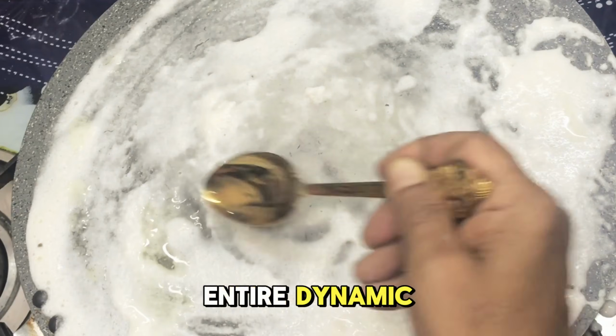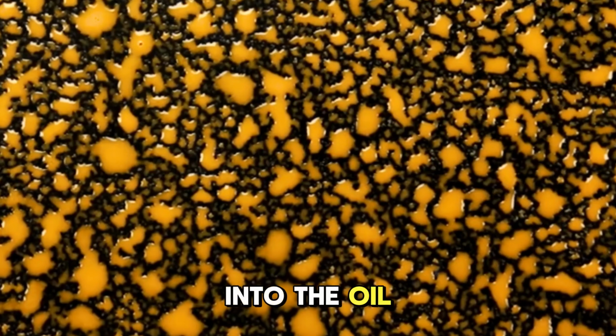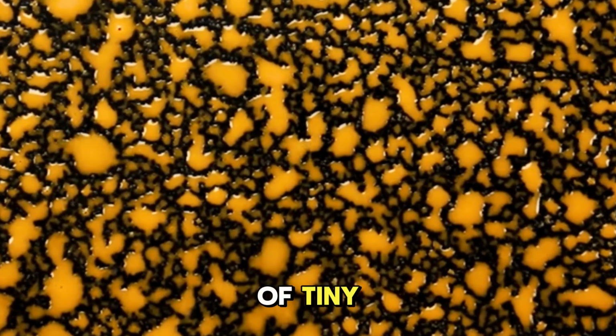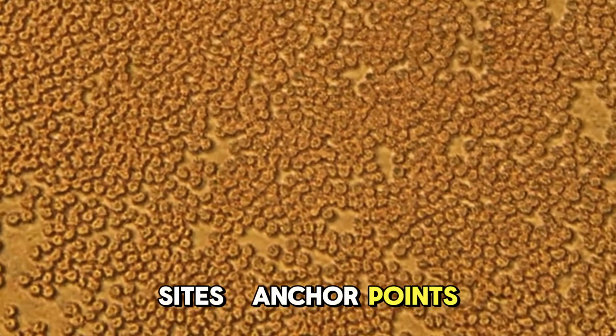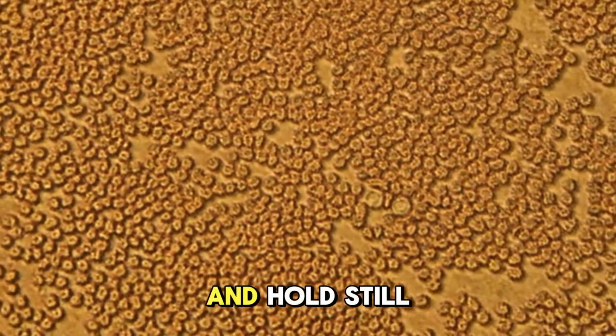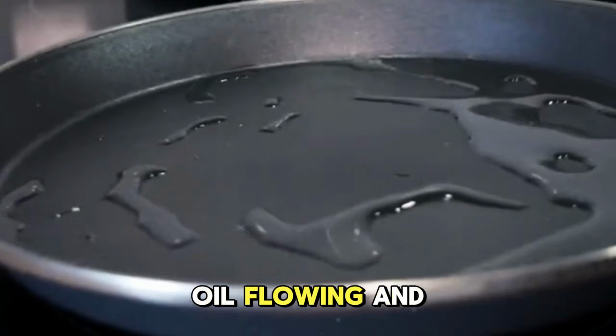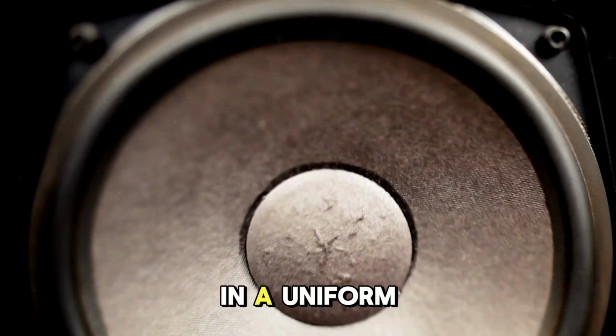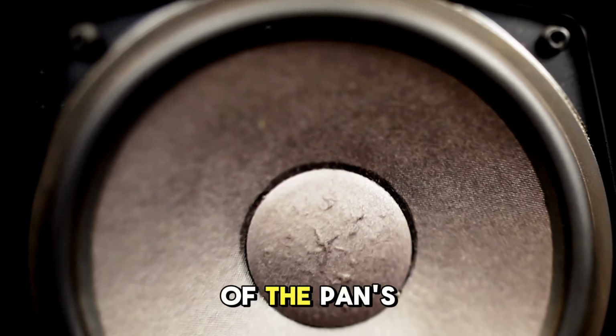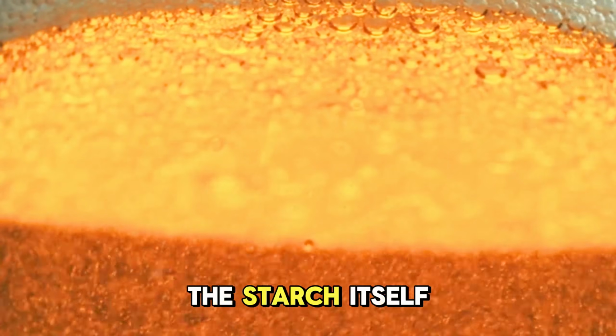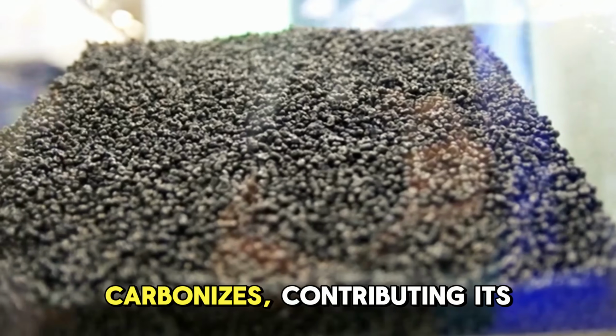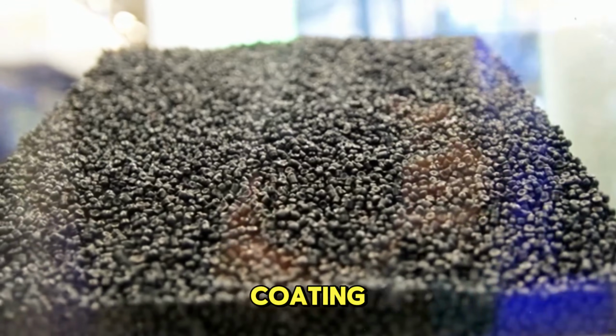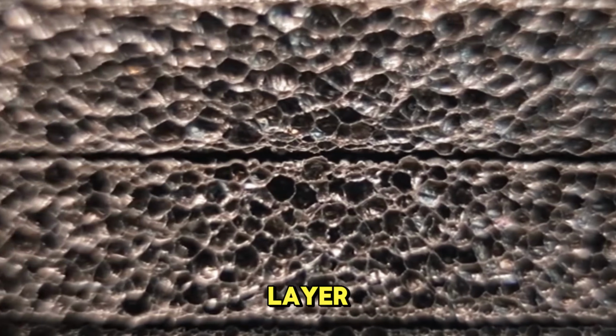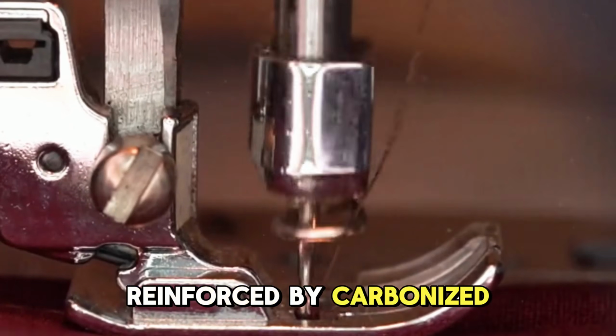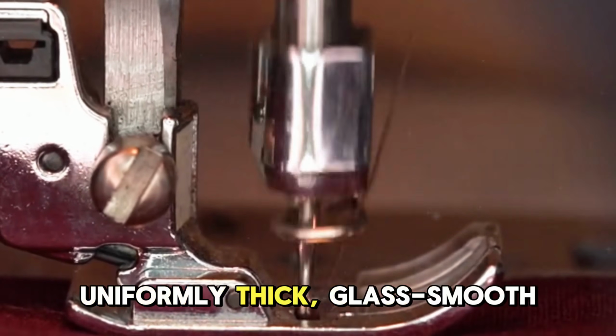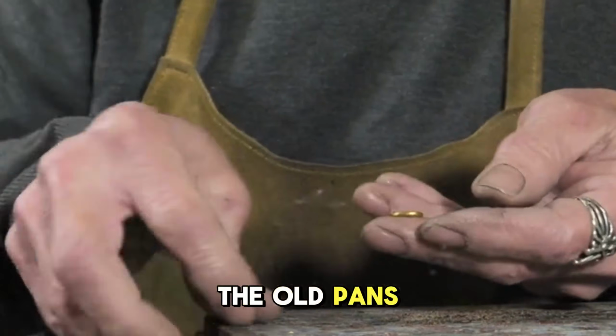Flour changes that entire dynamic. When you work wheat flour into the oil, the starch granules act as thousands of tiny nucleation sites, anchor points where the polymerization reaction can begin and hold still. Instead of the oil flowing and pooling, it gets physically suspended in a uniform film across every square millimeter of the pan's surface. As the heat climbs, the starch itself caramelizes and then carbonizes, contributing its own carbon matrix to the final coating. You end up with a composite layer, polymerized fat reinforced by carbonized starch, bonded to iron, uniformly thick, glass smooth. This is why the old pans feel different.